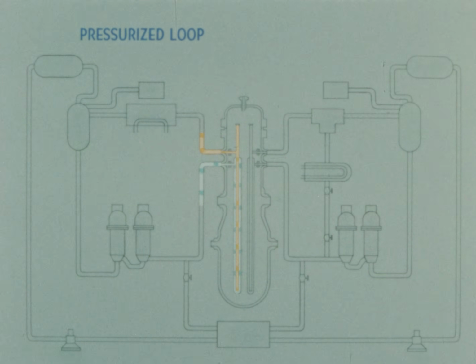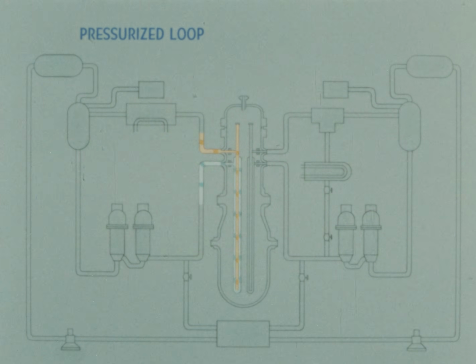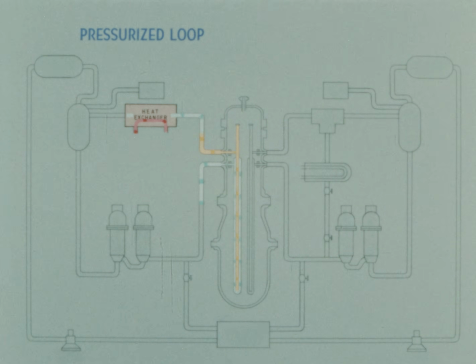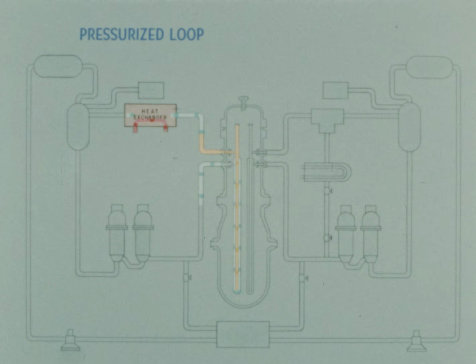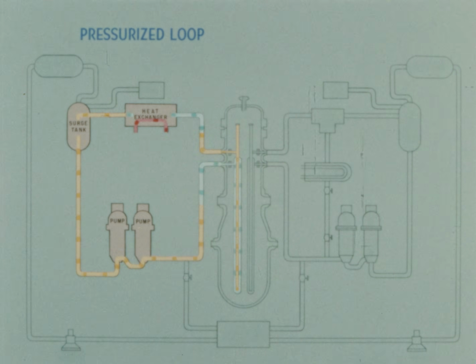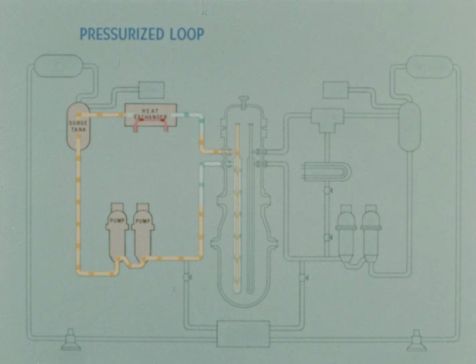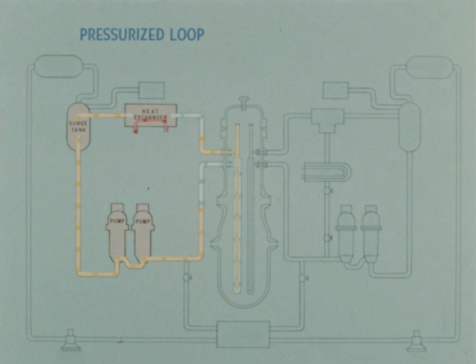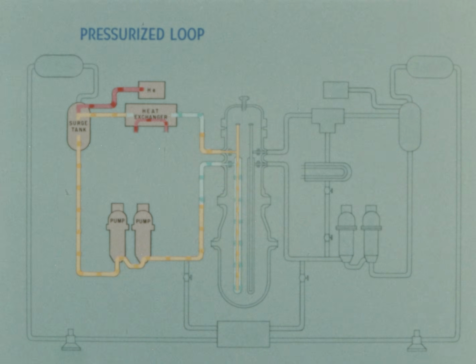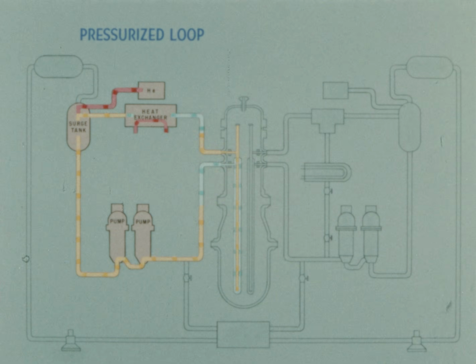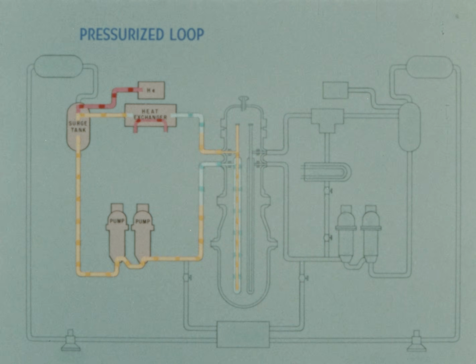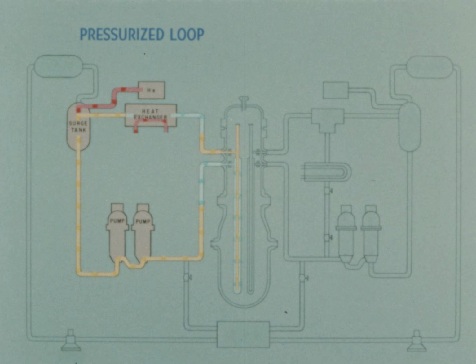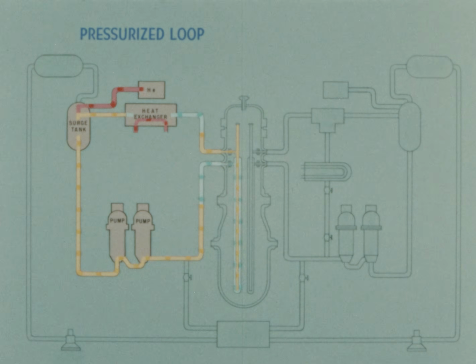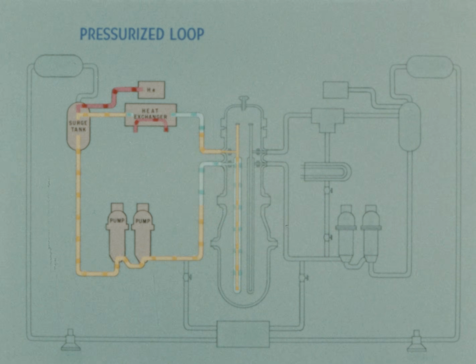Coolant is then circulated through the shell side of a D2O H2O heat exchanger. The cooled D2O is then circulated through a surge tank and back through 2 centrifugal pumps to the loop tube. The loop is pressurized with helium at the surge tank. Rupture discs between this gas line and the reactor pressurizing gas system provide for pressure relief of excessive loop pressure.